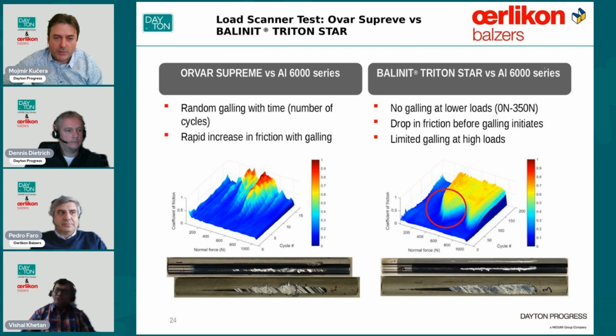So we had a situation where the load scanner test was used to find a good DLC coating. It was already explained to you by Pedro that DLC coatings or carbon-based coatings are very helpful in the aluminum stamping and punching industry. So here you see a comparison. On the left-hand side, a test done with steel against an aluminum 6000 series alloy, and when these two rods were rubbing against each other, you see in the graph the change in friction coefficient on the y-axis. On the x-axis you see the change in load, and on the z-axis the number of times the rod was rubbing.